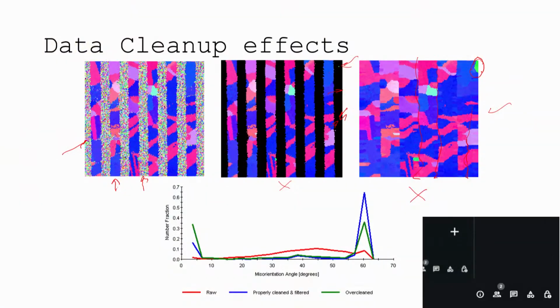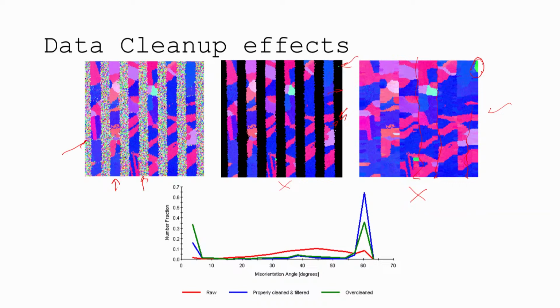And you can say it has to be that orientation, plus they have to have that confidence index. And so you can use orientation plus confidence, or just confidence, or there's a lot of ways to do it. And you can say, let's say only 2 data points have to be the same as the one in the center to clean it up, right? So there's a lot of options. A lot of ways to create fake data. That's what it is. So be careful.